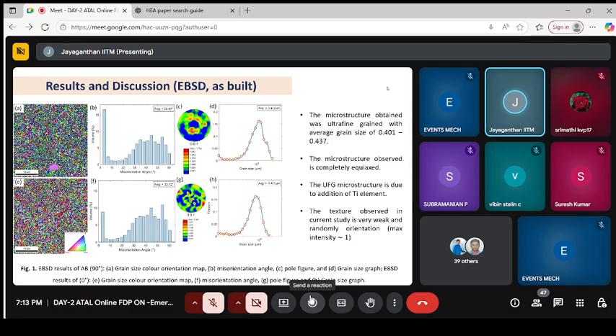Look at the microstructure through the camera. Look at their orientation. Through pole figure analysis, I want to understand the microstructure being produced through 3D printing. What is the grain size variation? From what size to what size does it vary? It is not desirable to have a very wide size distribution for the grains. Like I discussed about powder particle size, the 3D printed material also, when you see through a microscope, is all interconnected grains or crystals. The typical size and shape is characterized through EBSD microscopy, a camera attachment to the scanning electron microscope.